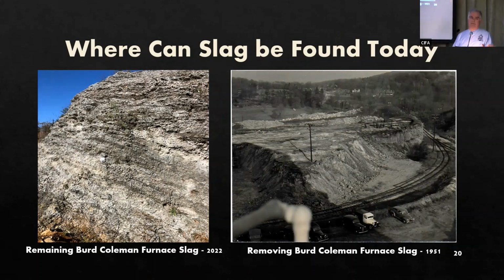So where can slag be found today around Cornwall? Well, because of the amounts of slag generated in Cornwall, slag can be found all over the place. Besides the relatively small pile that I already showed you next to the Cornwall furnace, slag can be found near and around the other blast furnaces that operated in Cornwall, including Anthracite Furnace, Coleman Furnaces, and the North Cornwall Furnace. Some of the slag has been removed and used for other beneficial purposes, such as road construction and railroad construction. And you can also find slag from the Coleman furnaces along the Lebanon Valley Rail Trail, especially just to the southwest of the Iron Truss Bridge here in Cornwall Center.